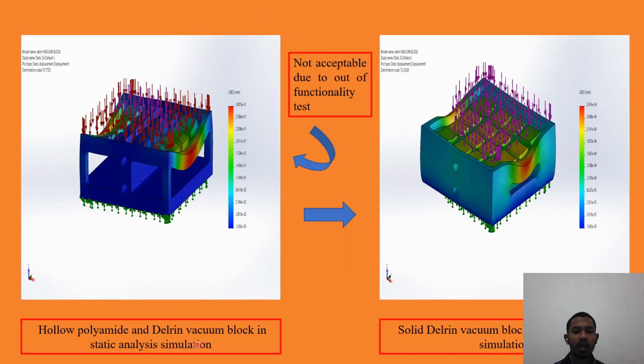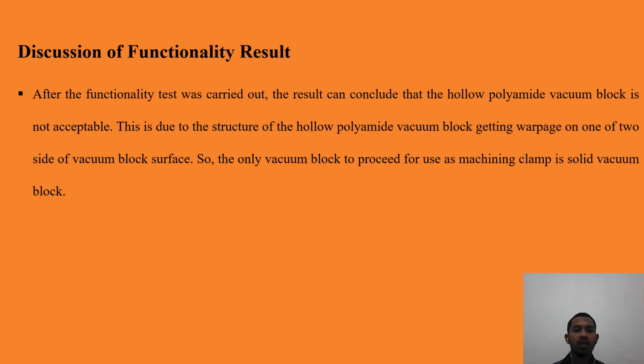The hollow polyamide and Delrin vacuum blocks in the static analysis simulation are not acceptable due to failing the functionality test, and I will proceed to the solid Delrin vacuum block in a static analysis simulation. Discussion of functionality result. After the functionality test was carried out, the result can conclude that the hollow polyamide vacuum block is not acceptable. This is due to the structure of the hollow polyamide vacuum block getting warpage on one of two sides of the vacuum block surface. So the only vacuum block to proceed for use as a machining clamp is the solid vacuum block.